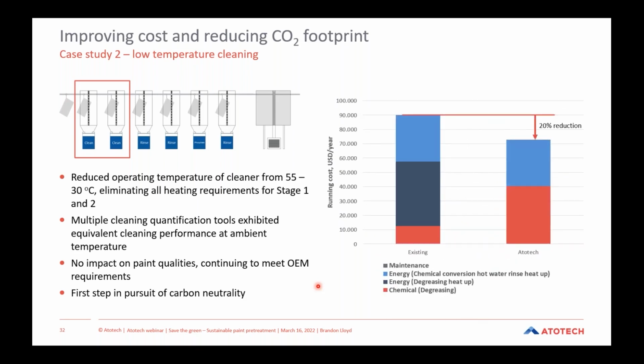So here on the right side, you can see some of the costs that were associated with the process. You can see that on an annualized basis, the existing chemistry had an associated cost of around $90,000 US per year. With the implementation of the Atotech system, you can see that we're able to reduce that by about 20%. And pretty much all of that is coming exclusively from the capability of reducing the energy requirement for heating the cleaner degreaser stage.